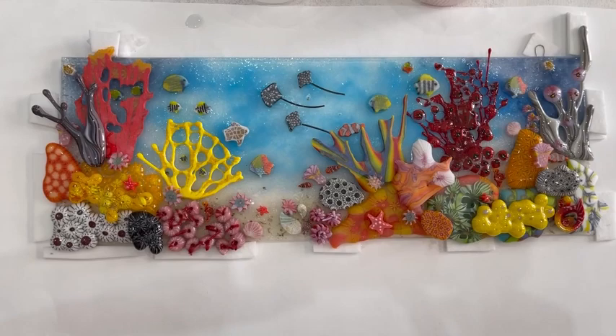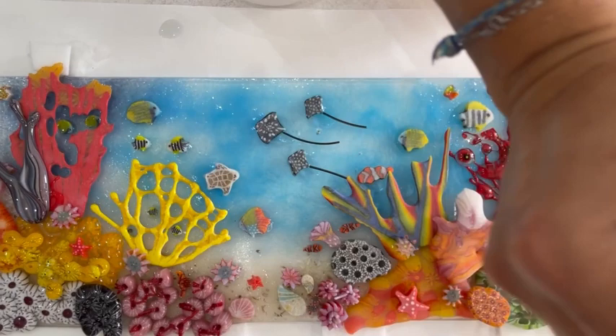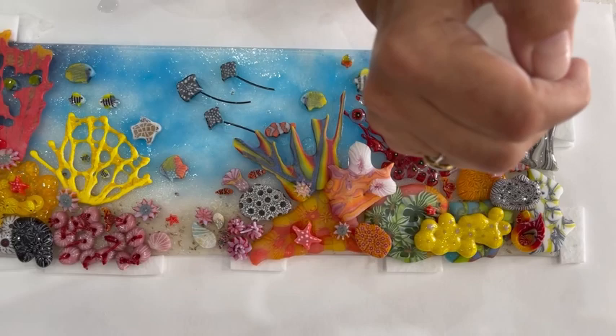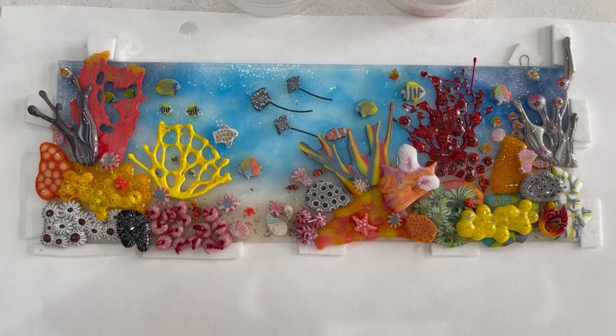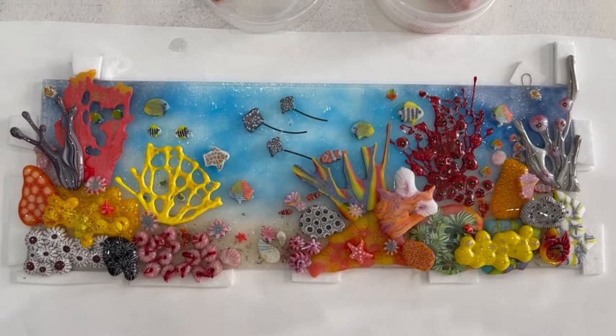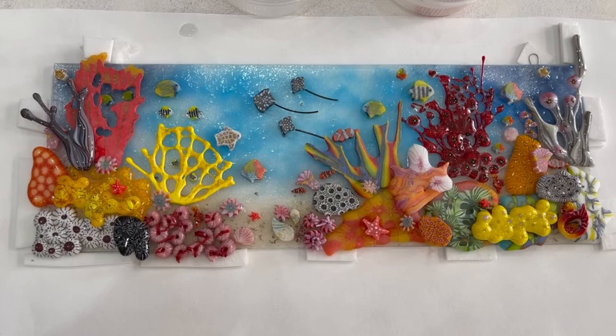I'm probably going to add a few more fish - where you see gaps, it's quite nice to think a little fish would like to hang out in that spot. It'll be exciting when we have even more fish. A couple more there - you can go more or less, it's entirely up to you how many fish you want on your coral reef. This is going to go in on a six-hour anneal, very long and slow, because this is masses of layers. It's also going to be quite a light fuse because I don't want to go too heavy and I want to keep as much definition as possible. Very light tack, long anneal, and praying to the kiln gods that everything comes out alright.